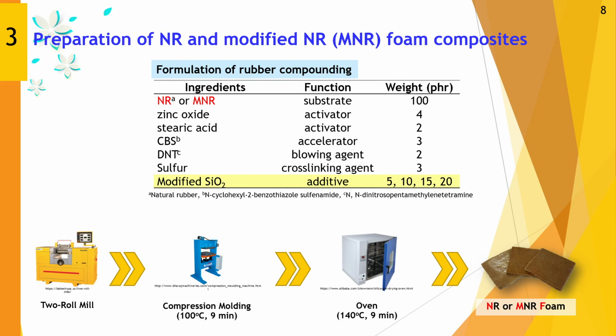The formulation of the rubber compounding is shown in this slide. All ingredients were mixed by using a two-roll mill, and then the rubber compounding was subjected to compression molding at 100 degrees Celsius for 9 minutes, and then to the oven at 140 degrees Celsius for 9 minutes. Finally, we could obtain the natural rubber or modified natural rubber foam composite.